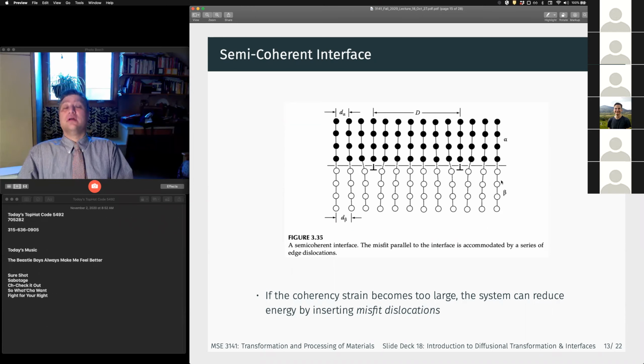This is really important in fabrication of semiconductor devices, right? So if you're depositing a material on a substrate, the first couple atomic layers are going to form a perfectly coherent relationship. But as you get thicker, the strain becomes too large, the strain energy becomes too large, and dislocations form, and it forms threading dislocations in your device, right? And this is a big area of research of Professor Grassman, right? Is understanding how to engineer and work with the formation of semi-coherent interfaces during the fabrication of semiconductor devices.